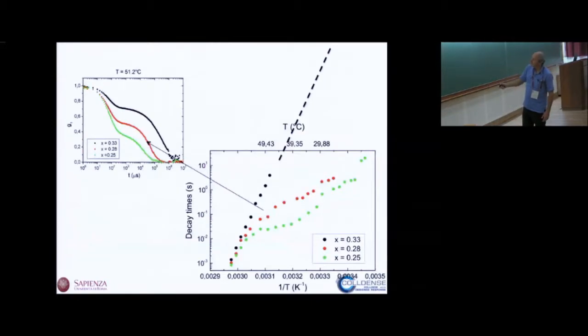So, and this is the 28, the red one. Now those are the ones with x=0.33, so no swap. It's Arrhenius. If you would continue this curve, of course you cannot do experiments, here is months, years, and so on. But this one is given by this slope over here. You see how much faster this system has become. It's not like the swap of Ludovic, but we have also gained 5 or 6 orders of magnitude in speed up thanks to this swapping process in DNA.